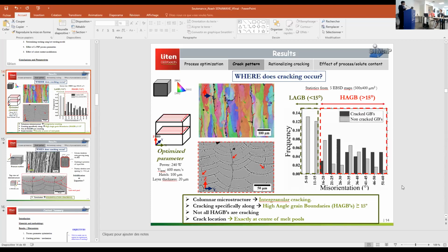And for me, the propagation can be due to several different aspects. For example, if two dendrites are growing in a particular way, and the space between the interdendritic region is more than the liquid feeding can fill, which is not able to liquid fill between the two dendrites, and if this condition is maintained all the way, you might have a propagation of cracking. So this is further after the cavitation pressure has been reached. In our study, we never looked into the propagation aspect of the cracks. It was all the time the initiation aspects.